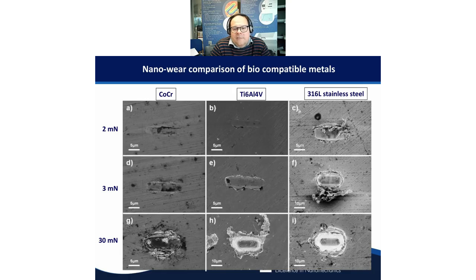And what you're seeing is that some of these materials behave very well in terms of a very, very small amount of debris outside of the wear track, on this titanium 6-4 here. But then at the higher loads, it's probably the worst in terms of debris production. The stainless steel at the low loads looks pretty poor in terms of the quantity of debris that's removed from the wear track. But comparatively, its performance has remained relatively stable across the load range. So we can start to assess pressure and environment and load cycle number sensitivity of these materials together.